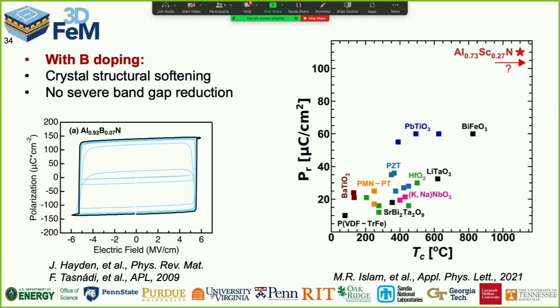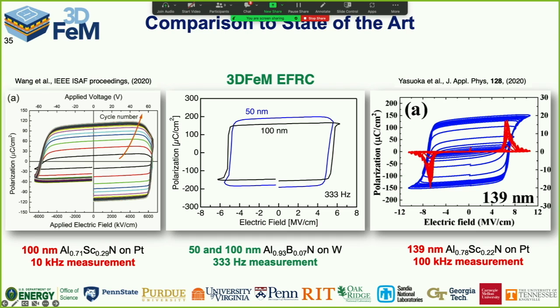So these materials are really different from conventional ferroelectrics. This is a plot of the remnant polarization as a function of the Curie temperature. Here's what we're working with, only we have to speculate that the Curie temperature is way off this board, somewhere in the next room over there. They're very different. Enormous polarizations, incredibly temperature stable. And if you look at aluminum boron nitride compared to its analog aluminum scandium nitride, you can see why we are interested in it.